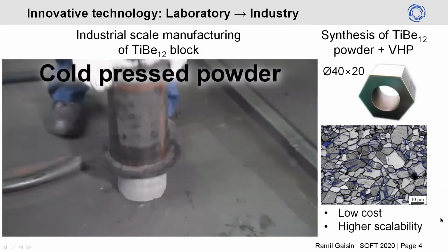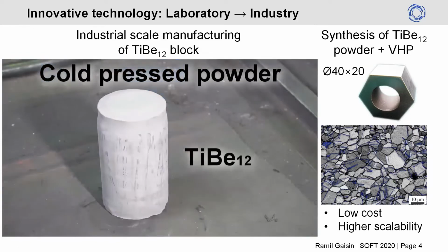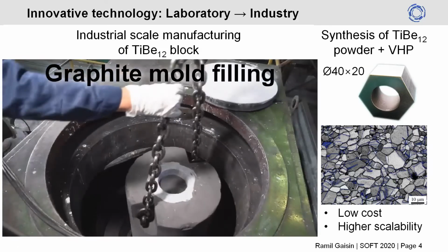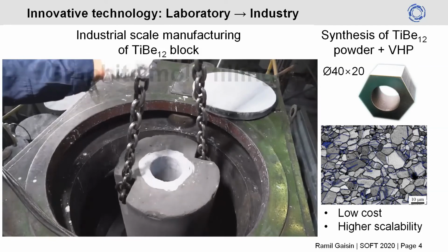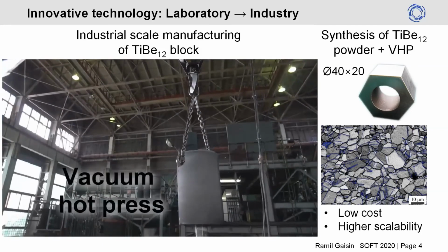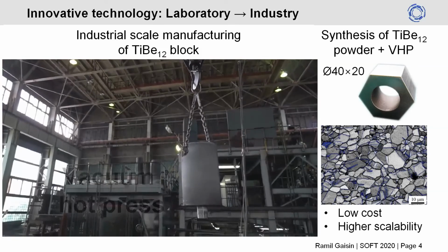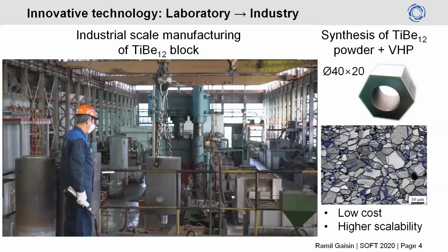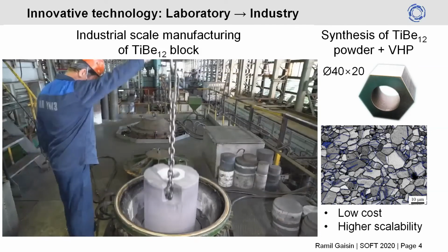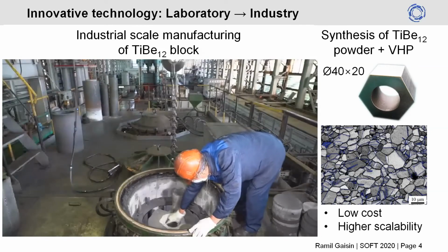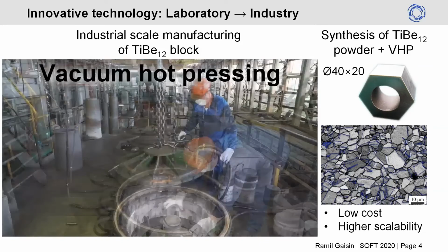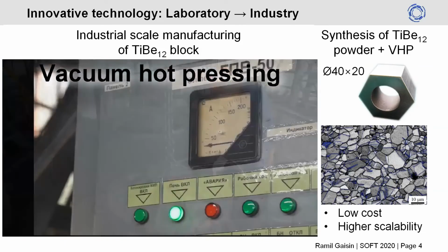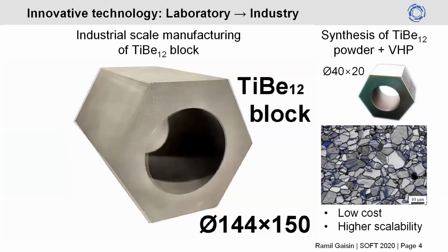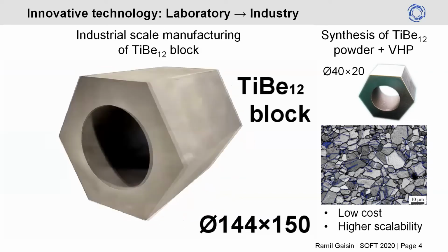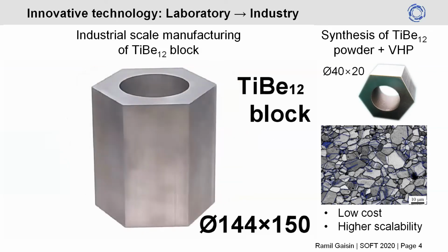After cold pressing of already synthesized beryllide powder, a graphite mold is filled with it. Then the mold is transported to vacuum hot press here on the left. You see, this is a real plant with huge machines and equipment. Last steps of preparation. Then the chamber is closed and vacuum hot pressing begins. After pressing and final machining, a full-size block with 144 mm in diameter and 150 mm in height was obtained.